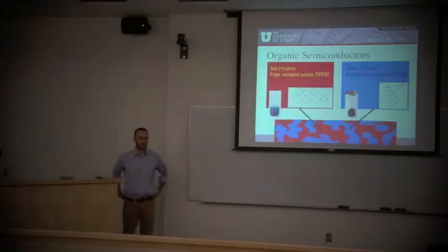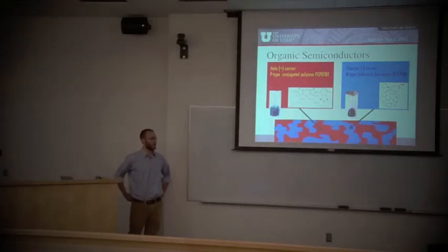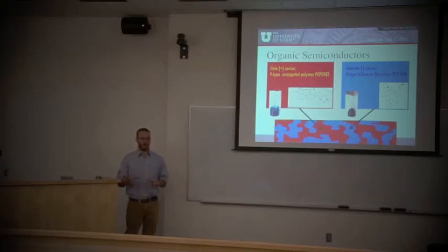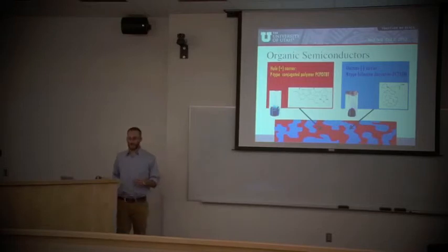I'm working with organic semiconductors. These differ a little bit than inorganic semiconductors like silicon. Silicon is a single material, and so you can do things like band bending, which is seen there. It smoothly separates the charges. But organic semiconductors, these are discrete molecules. It's not a single crystal of material. What you have to do is you have to add two different types of materials. You have to add a donor and an acceptor material.